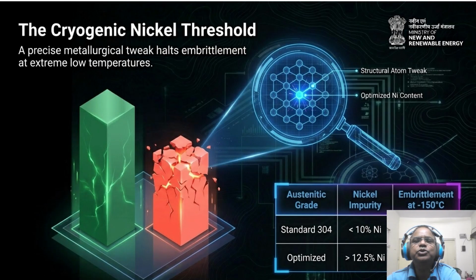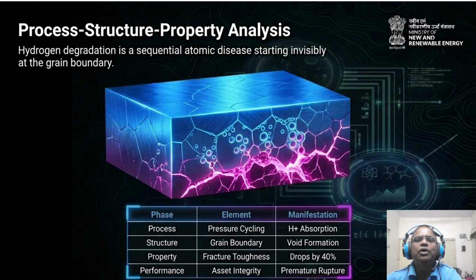To understand why this nickel threshold matters, we must apply the PSPP framework to the degradation sequence. Our next slide is on this process structure property analysis, which is important to know about hydrogen degradation, a sequential atomic disease. Follow the 3D block schematic on the screen. It starts at the surface and moves inward. This is the PSPP framework: process, structure, property, and performance. As shown in the table, the process is your daily pressure cycling. This forces H+ absorption into the structure, specifically at the grain boundaries, leading to void formation.